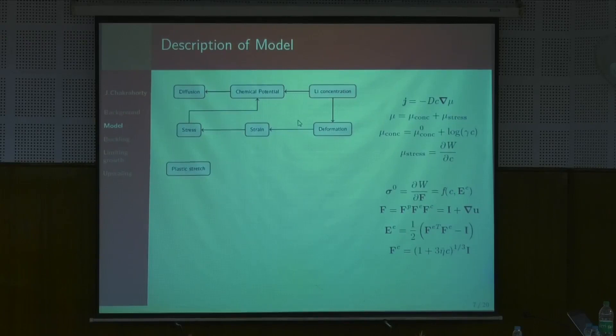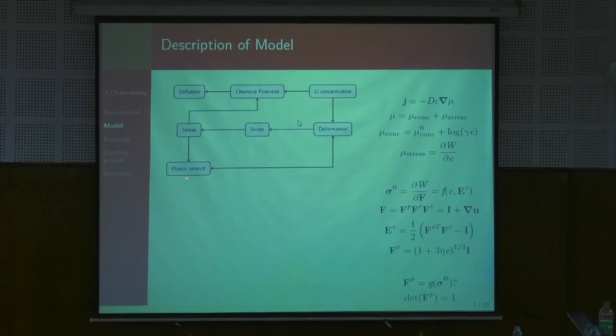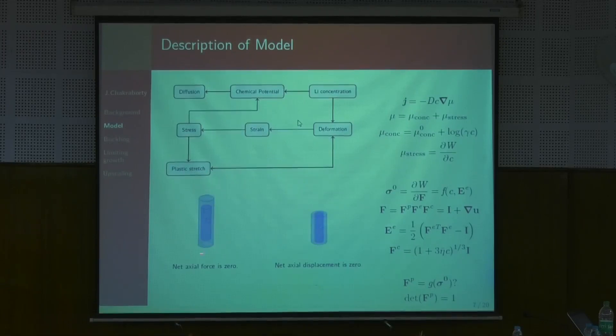Over and above this, I have something devilishly difficult: plastic stretches. These plastic stretches are intrinsically connected to the stresses — when the threshold level of stress is exceeded, the material goes into the plastic region. These plastic stretches are also intrinsically connected to the deformation. So these are the main things I have to keep track of, along with extra conditions: for the first case, the net axial force is zero and net axial displacement is zero.